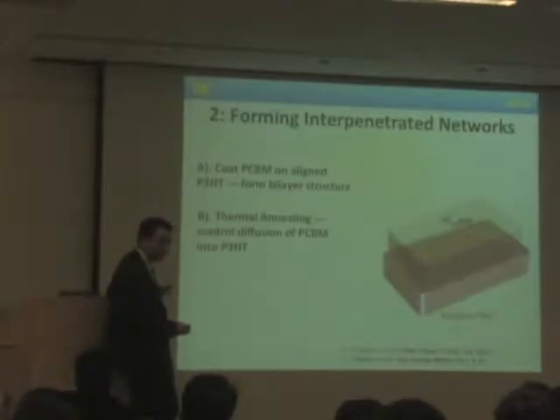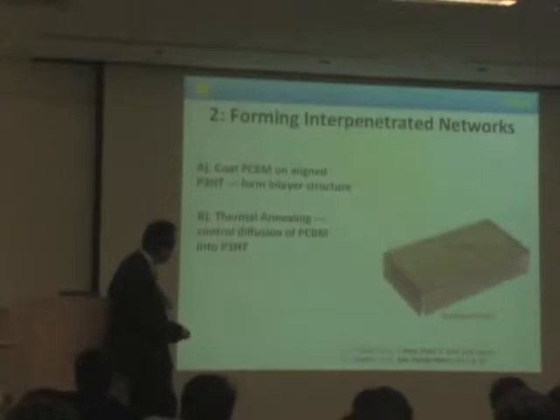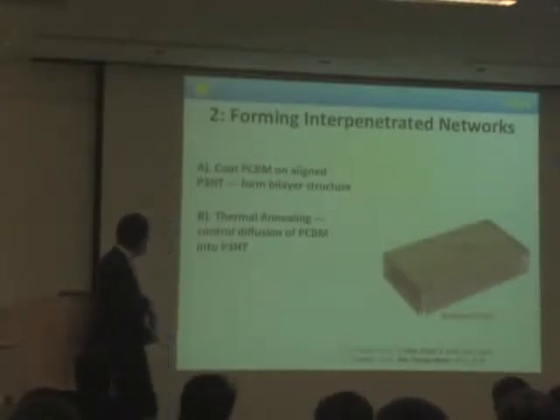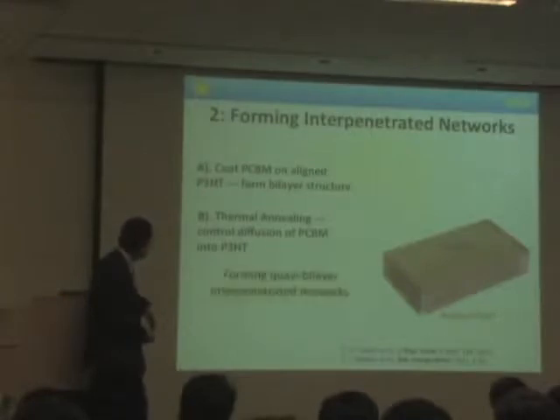We want to orient the polymer film, and we want the PCBM to diffuse into it. That's why after we rub the P3HT, the PCBM diffuses into it. Nicely well done. So Ben was very happy because at least his invention has some use, not necessarily for the device, but at least to prove the oriented solar cell. So we have a quasi-bilayer interpenetrating network.